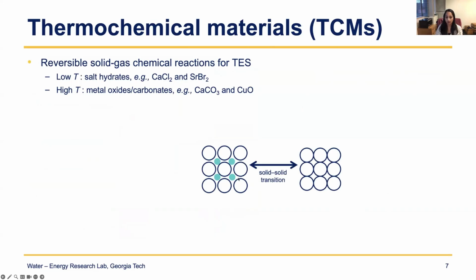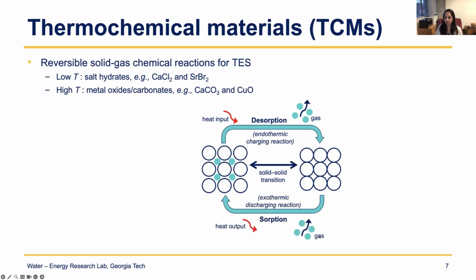So you start off with one solid structure. Let's say low temperature, we mainly work with salts, salt hydrates. Essentially it's a salt that has a certain number of water molecules attached to the crystal structure itself. And if we heat up the salt, it gets dehydrated. That's a desorption reaction, and the water vapor, which is the gas in this case, will leave. So this is how we charge, because we've put energy in. And then we get a second crystal structure, the new phase. And then when we want to discharge, we would reintroduce the gas. The sorption reaction occurs. This is exothermic, and so heat is released in this reaction, and that is the heat that you would use for your process.